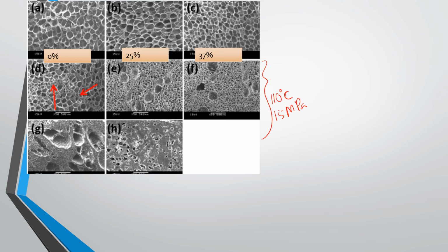They indicated that these first three pictures show there is no crystal growth, since the size of the bubbles increases as it goes from letter A to C. They mention how there's no crystal growth in the first few pictures, which happened within 12 minutes under the conditions that I mentioned before. However, when the nucleation reaches 49%, in picture D, the crystal region shows a slowly growing bubble diameter larger in some areas, especially at the interface between the crystals and amorphous areas. The crystal growth is shown by the red arrows.